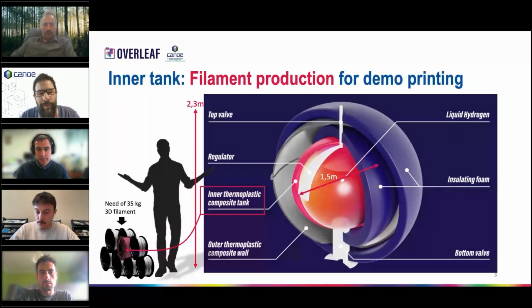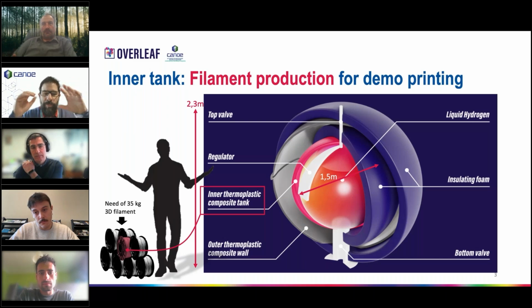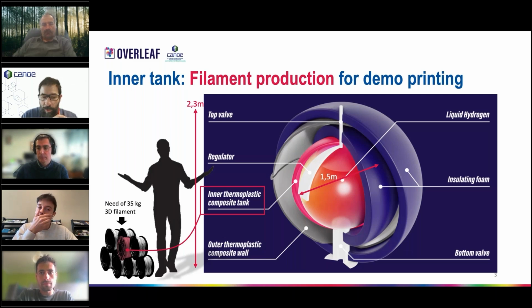In this webinar, we talk about the inner tank. The inner tank is the pink part in this picture. This is the part where the liquid hydrogen will be stored at very low temperature, about 20 K. And the size of this spherical object is pretty impressive because it's about 1.5 meters diameter. That means it represents a lot of material to produce, especially for 3D printing. It's something like more than 35 kilograms of filament spool that we have to manufacture.